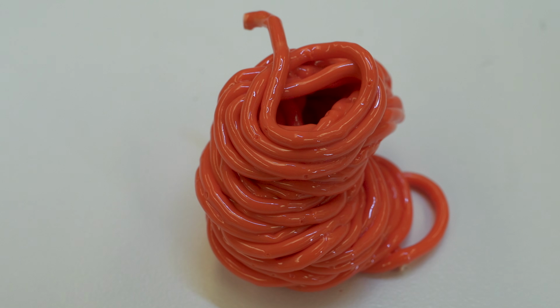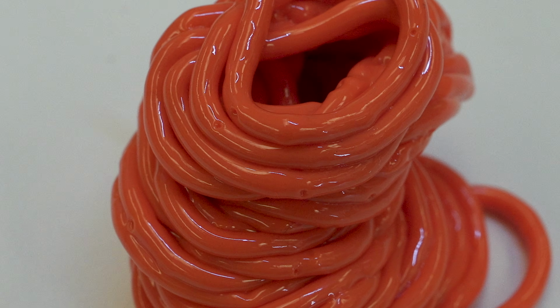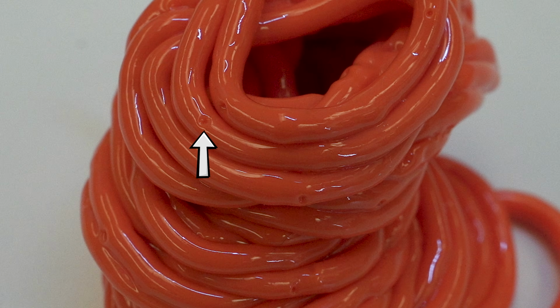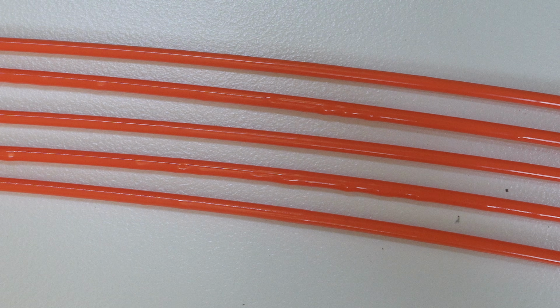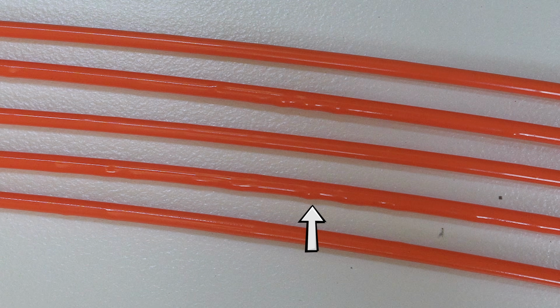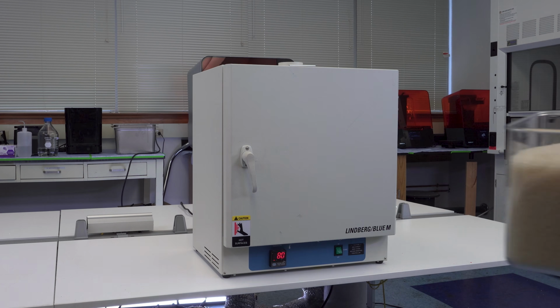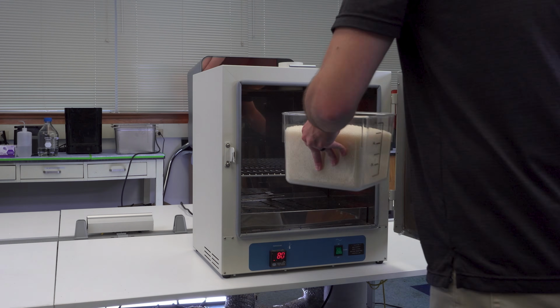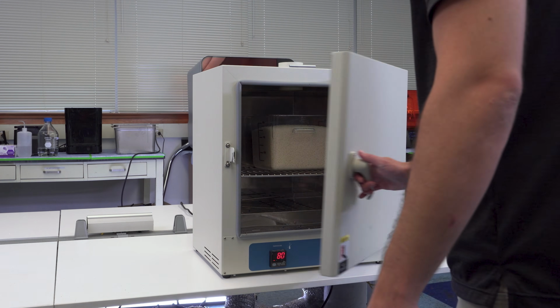of this room. The second issue is that ABS is a hygroscopic material, meaning it readily absorbs water from the air. In some cases, up to 5% of the material's weight can be water. When this moisture gets into the barrel, it boils and its gas escapes through the die, causing voids in the filament. Rough filament is usually a telltale sign that the pellets went into the hopper wet.